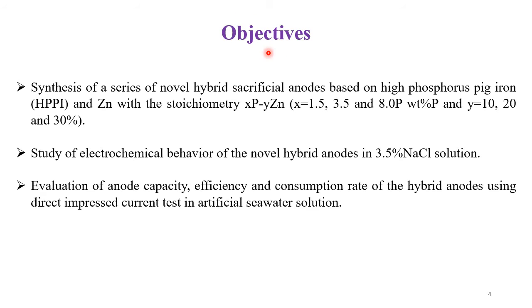So the objectives of the present talk are synthesis of a series of novel hybrid sacrificial anodes, based on the stoichiometry xP yZn, where we have varied the zinc between 10 to 30%, and then studied the electrochemical behavior in 3.5% NaCl solution, and also evaluated the anodic capacity, efficiency, and consumption rate.